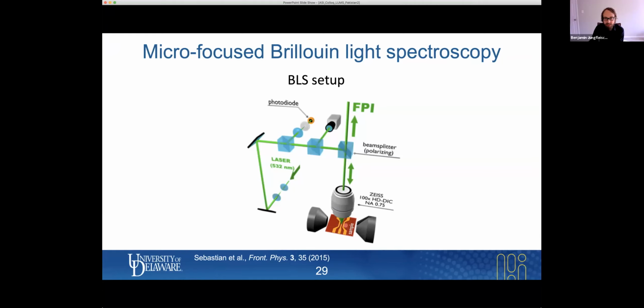So we placed our sample here under a microscope objective lens. We have here a 2D scanning stage with an accuracy of about 20 nanometers, and we have a magnetic field. This light is focused onto the sample and then sent back to the Fabry-Perot interferometer, where we analyze the frequency shift. We have also a photodiode for adjusting of the focus and a CCD camera to see where we are on the sample, and we also use some pattern recognition.